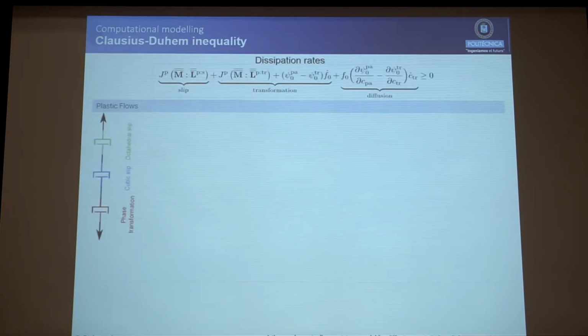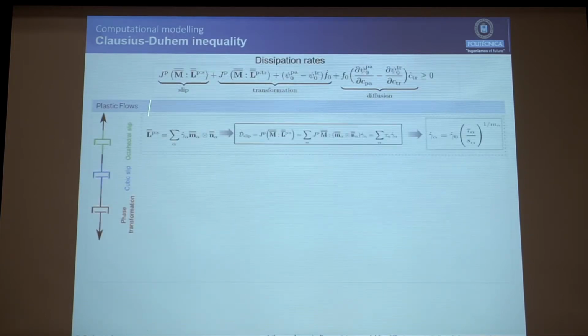So let's start with the slip system. If we have cubic slip and octahedral slip, we include the velocity gradient just as in standard crystal plasticity theory. We include that into the dissipation rate, and we get to an equation where we have the plastic multiplier multiplied by the driving force for this mechanism, which is the resolved stress. And we have included this driving force into a standard power law, and you get this standard power law equation.